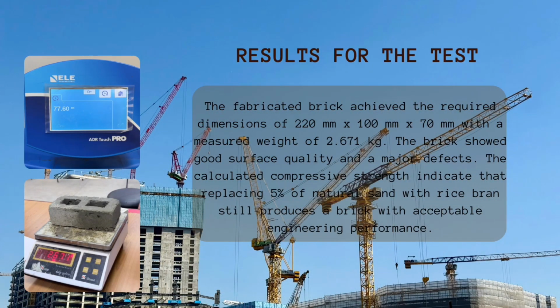Based on the experimental results, the fabricated brick successfully met the required dimension of 220 mm by 100 mm by 70 mm. The measured weight of the brick was 2.671 kilograms. The brick surface appeared smooth and no cracks were observed. The calculated density and compressive strength demonstrate that replacing 5% of natural sand with rice bran still produces a brick with acceptable physical properties and structural performance.